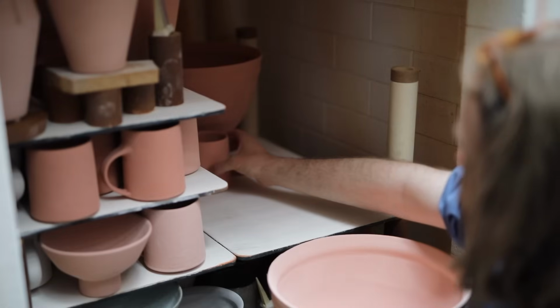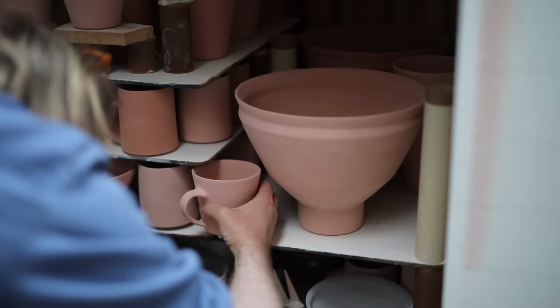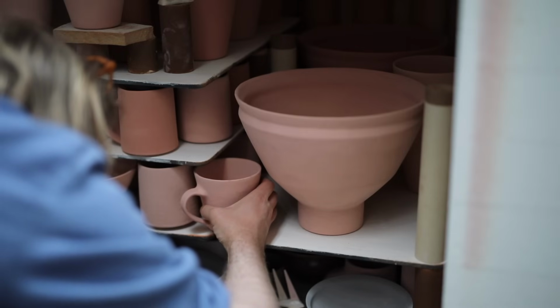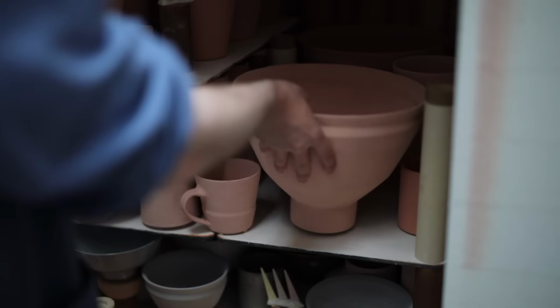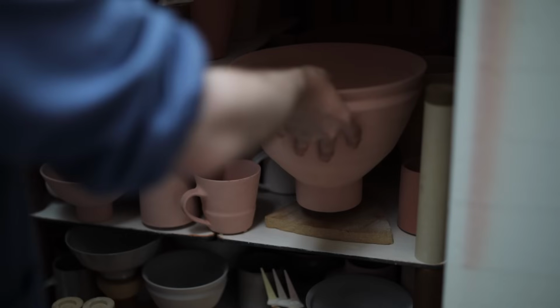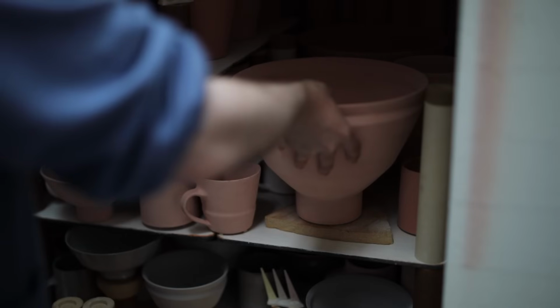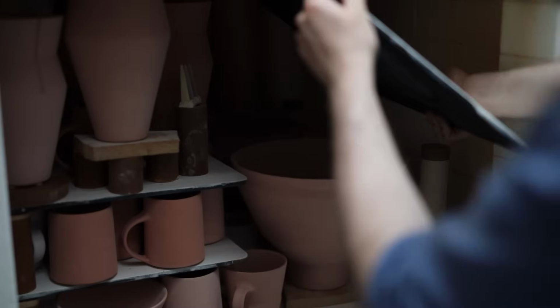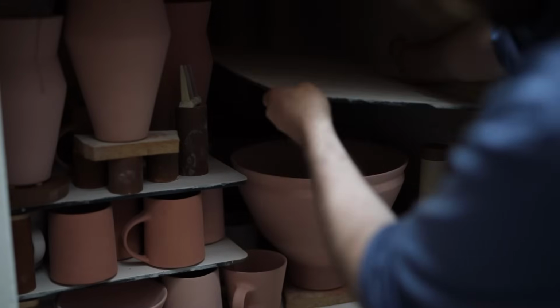I'll be firing both of these bowls side by side in the kiln, with every single pot inside this kiln load being carefully placed so that absolutely nothing touches. Otherwise the glaze that coats them will fuse together and they'll have to be torn apart afterwards, a process that normally destroys both pieces. I decided to place a bit of shelf underneath the bowl just to give everything on this layer a bit more space, and once I was happy with everything, I can place another kiln shelf on top and fill the rest of the void above.